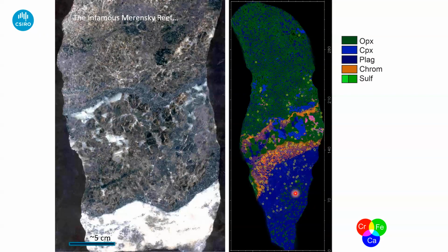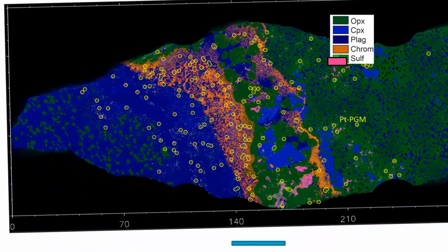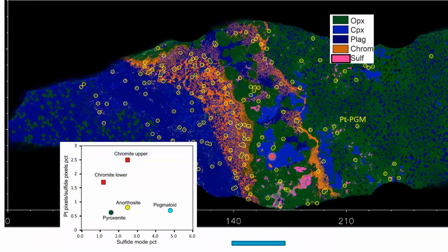What you see is that there's a sort of peak of platinum grains, particularly associated with the chromite seams, a little bit extending up into the pyroxenite. But every single one of these platinum hits, called platinum hits because they might be composite grains, every single one of them is associated with sulfide without any exceptions. But the other interesting thing is that if we look at the proportion, so we do a number count of the platinum hits versus the sulfide mode derived from this image, what you find is that the proportion of platinum to sulfide is much higher in the chromite seams than it is either in the anorthosite below it or in the pyroxenite, higher by a factor of maybe 4 or 5.